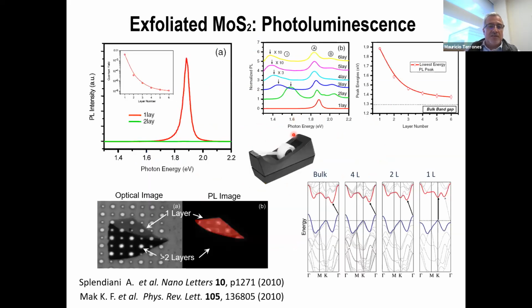So just as a sort of introduction, this is work that was done by Kin Fai Mak and Tony Heinz's group in 2010, and they exfoliated molybdenum disulfide, and they say, well, there's a monolayer here, and there are 2 layers here, and when they had the monolayer, you have this huge photoluminescence (PL) signal here, right? Which is related to a direct band gap.